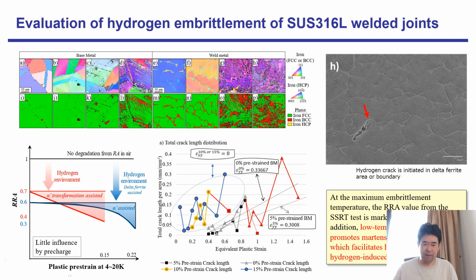The left bottom graphic is a schematic summary of this SSRT test. The horizontal axis is the pre-strain amount at 4K. The vertical axis, RRA, is remarkably decreased by the pre-strain amount. This is due to microcrack formation started in the early deformation stage.